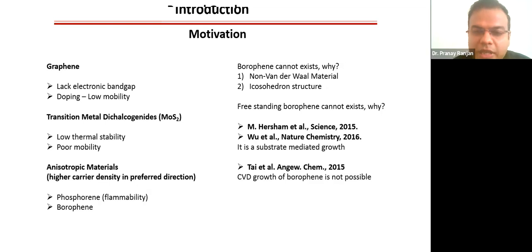However, a few seminal results from Mark Hersam's group at Northwestern and Wu et al. from the Chinese Academy of Sciences showed that borophene can be deposited on a substrate. And they did this calculation and hypothesized that it's a substrate-mediated growth. That means the atoms of the substrate govern the growth of the borophene. Again, they said that it cannot exist as a free-standing sheet.